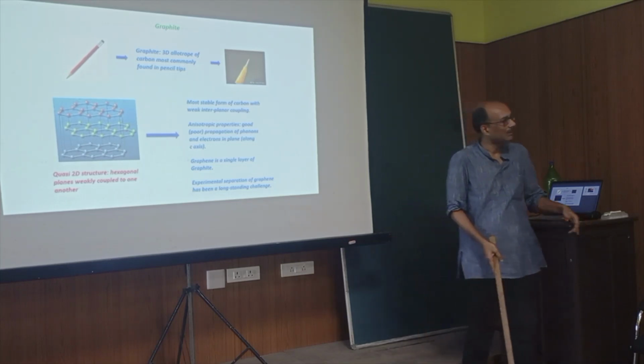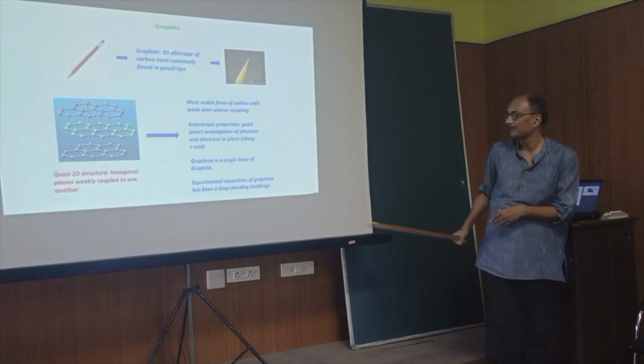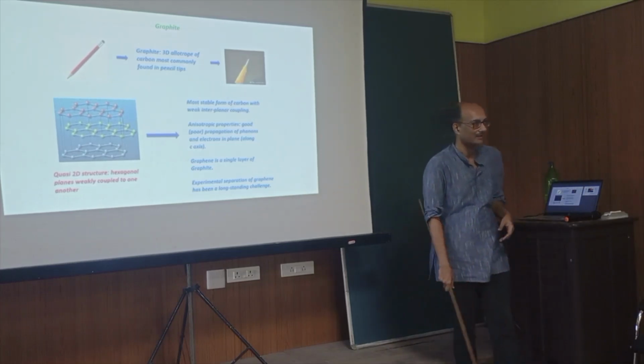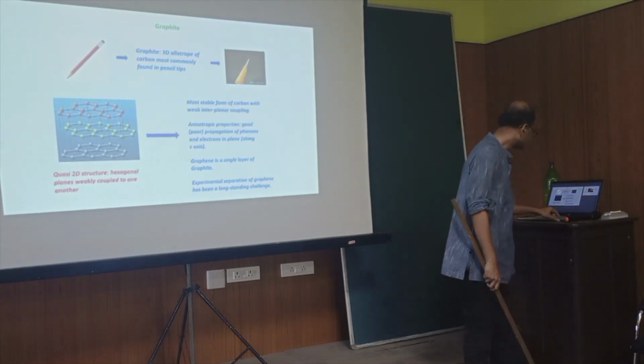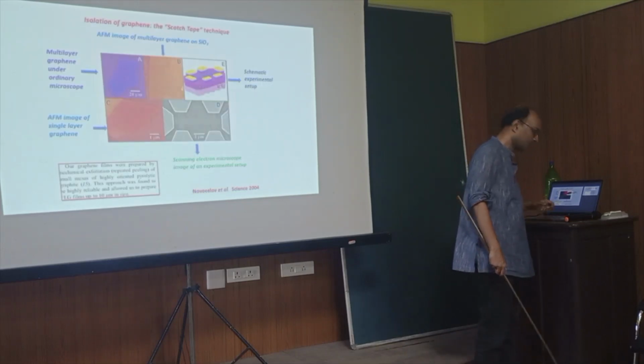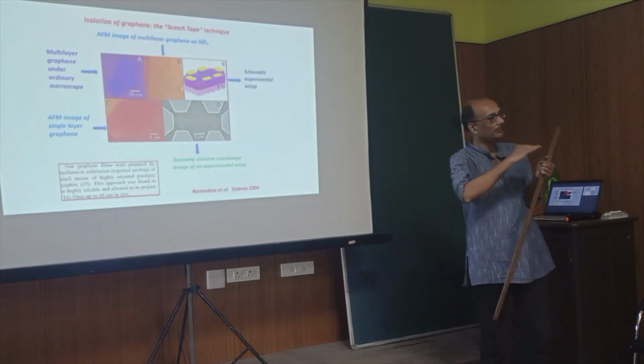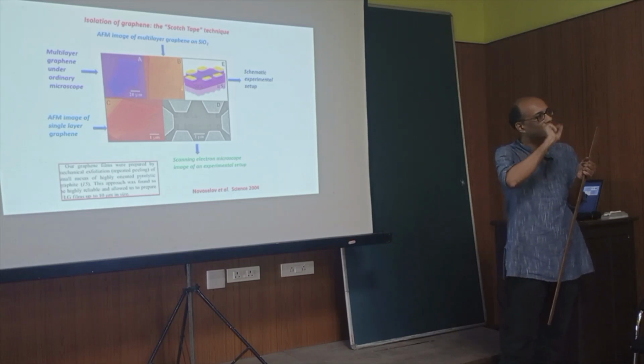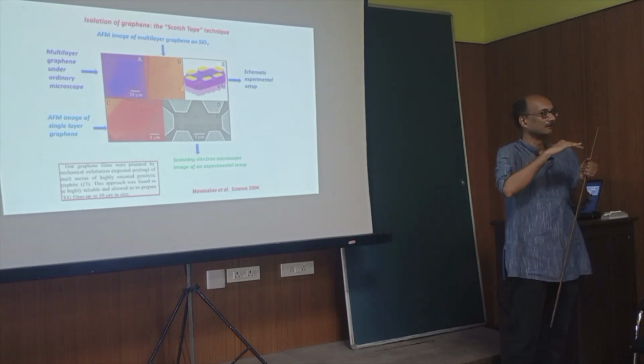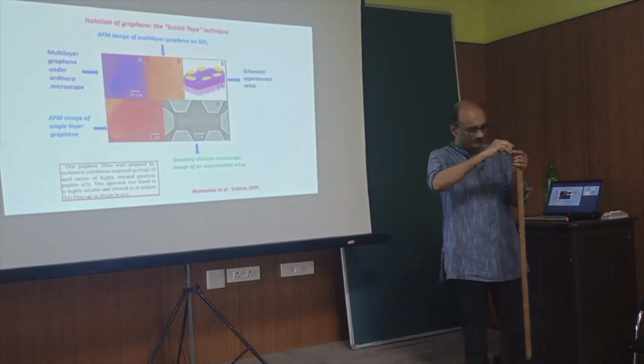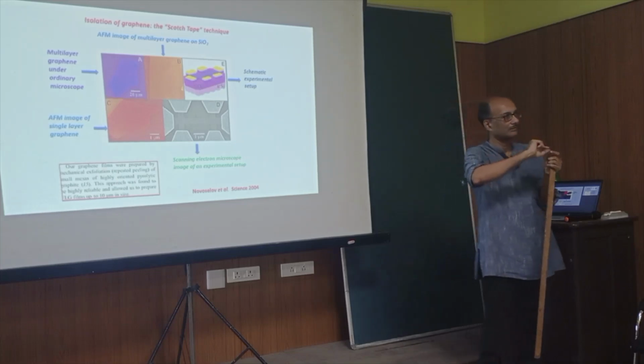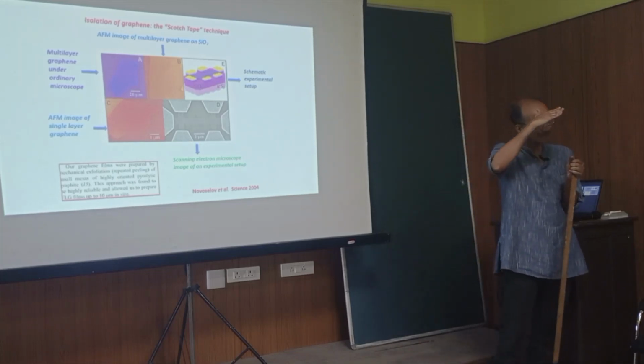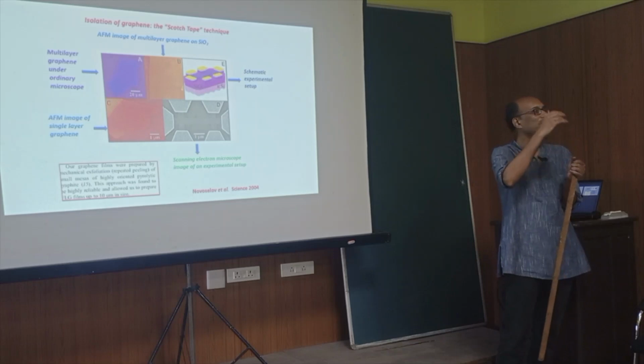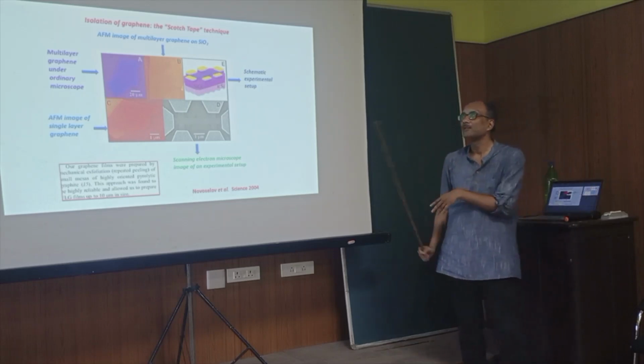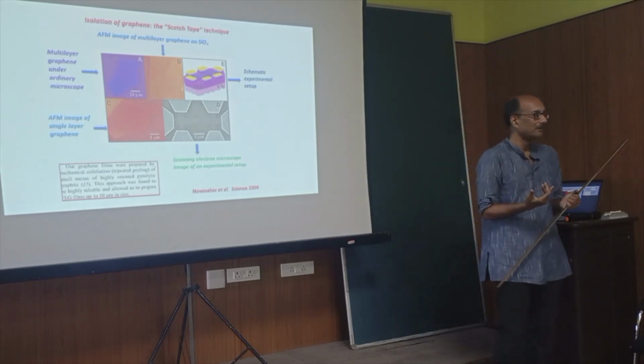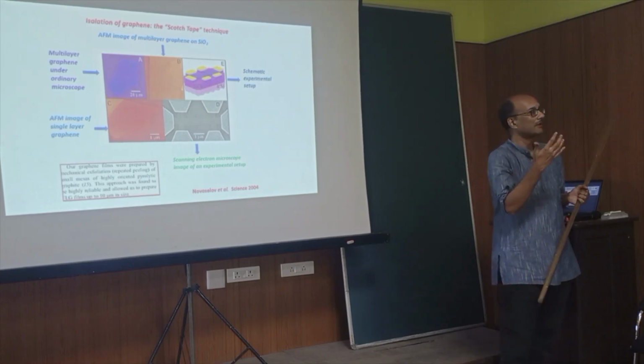Experimental separation of graphene has been a long-standing challenge, and people have been trying this for some time. The reason is the following. Typically, to get these few layers of graphite, what people do is cleaving. You take a graphite crystal and start chopping it up, very finely. But no matter how finely you do this, you get to a few hundred layers, but not fewer.